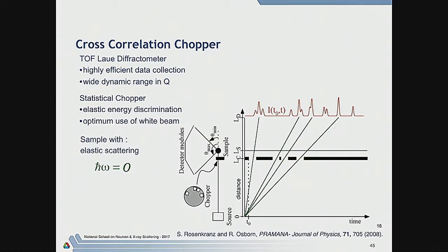Okay. But supposing you have in this sample inelastic scattering. So when it gets to the sample, then the neutron might lose energy. And so there might be, say, an inelastic peak. One here, there's another inelastic peak here, another one here, another one here. And if you're at higher temperature, then you might get an energy gain peak as well. Neutron gains energy. If you imagine that this distribution of intensities is roughly Q independent, you might get a whole series of these three-peak structures produced by all of these beams.